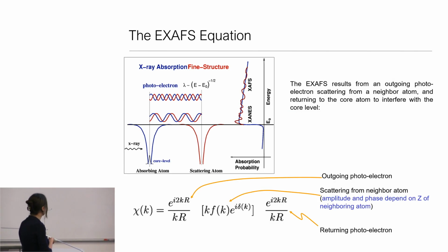This is the actual XAFS equation. So we start by basically having an exponential that describes the outgoing photoelectron wave, and also an exponential that describes the returning photoelectron wave. And then what needs to happen is it's going to be modulated by both the amplitude, the f of k parameters, and the phase, the delta k parameters of the photoabsorber. And these parameters will depend on the nature of the neighboring atoms.